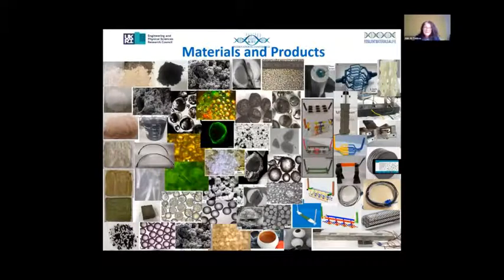So if we look at those in particular groups and starting from left to right, we've been exploring a range of mineral additives and inclusions, for example, expansive minerals and crystalline admixtures for crack closure, and layered double hydroxides and zeolites in calcined, functionalized and intercalated forms for self-immunization against corrosion. We've also been looking at carbon-based materials, graphite, graphene, carbon nanotubes, and a range of fiber composites, mainly for self-sensing applications.